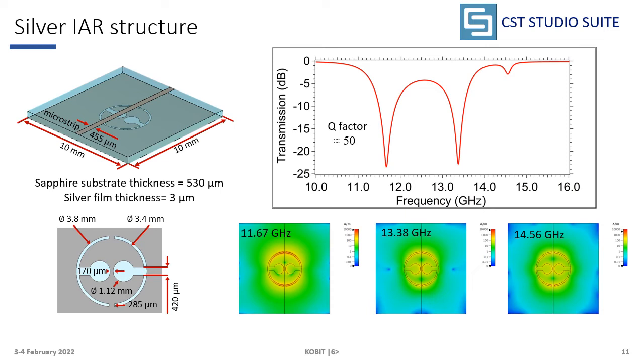When we look at the field distribution at the resonant frequencies, for the first mode we obtain a distribution similar to the superconducting resonators. For the first mode, the magnetic field distribution is localized around the outer conducting region, while for the second mode, the magnetic field distribution is no longer localized at the central conducting region. It spreads all around the conducting edges of the pattern, and there is also a small absorption peak, which is not so important for the study.